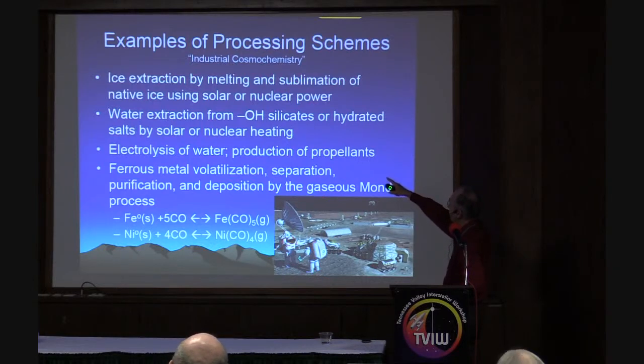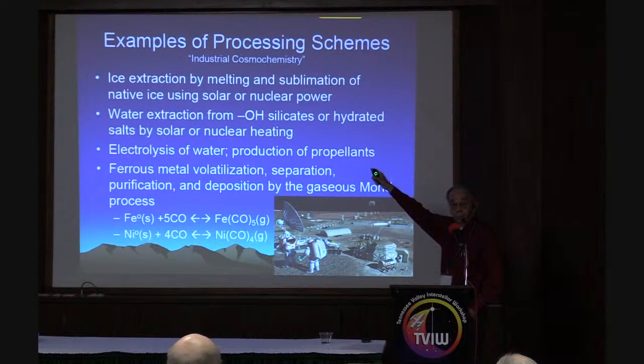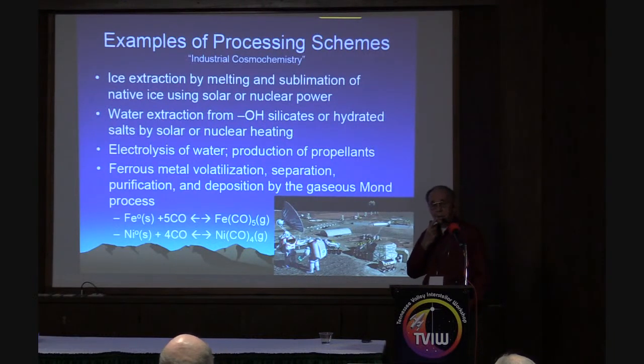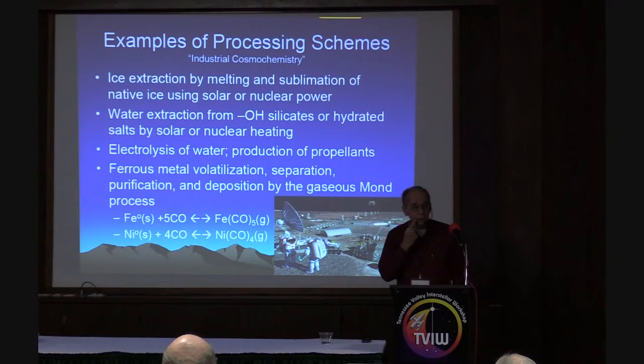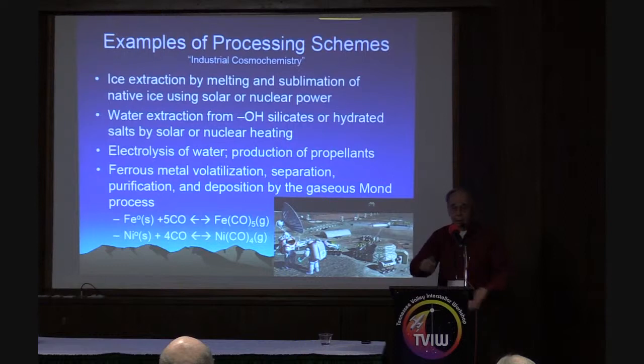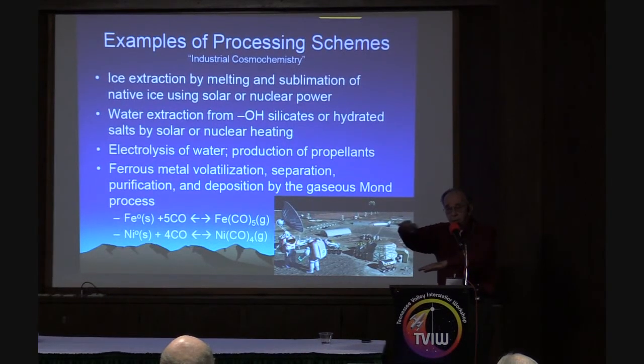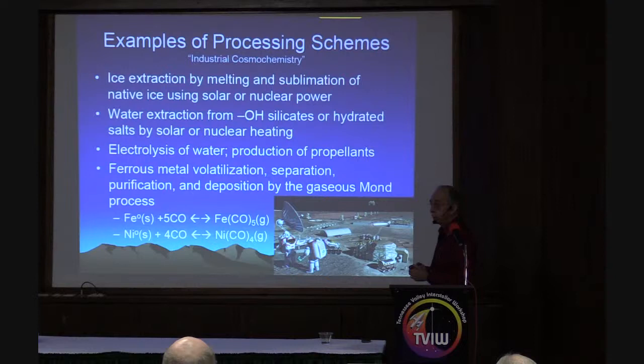Examples of processing schemes: ice extraction and melting, by melting or sublimation. Water extraction from silicates, micas, layer lattice silicates, phyllosilicates, clays. They have silicate sheets with hydroxyl attached to the silicates and, in many cases, with interlayer water of hydration between those layers. Some micas contain so much water that if you heat them up, they puff up like popcorn.